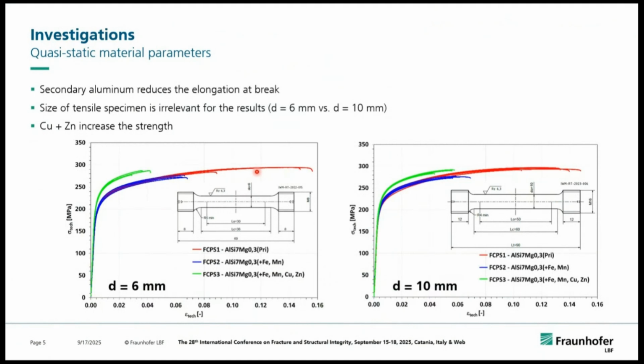On the other side, we made the same tests with a larger specimen to account for some size effects. The results were comparable, so we could not see, at least in this region, a strong influence from size effects coming from the specimen.